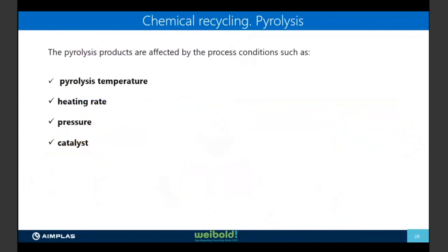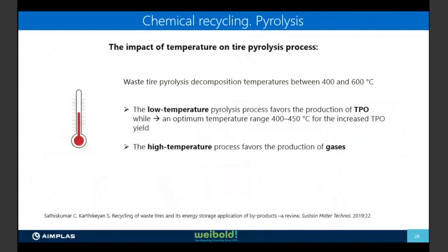Okay, talking about the pyrolysis process itself, these pyrolysis products are affected by the process conditions, mainly the pyrolysis temperature, the heating rate, the pressure, and the catalyst. So, as regards the temperature, I think that I have already said that pyrolysis temperatures were between 400 and 600 degrees. The low temperature pyrolysis process favors the production of TPO, the oils, and the optimum temperature range goes from 400 to 450 for increased TPO yield. And the high temperature process favors the production of gases.